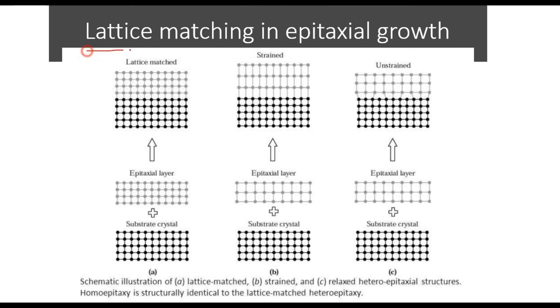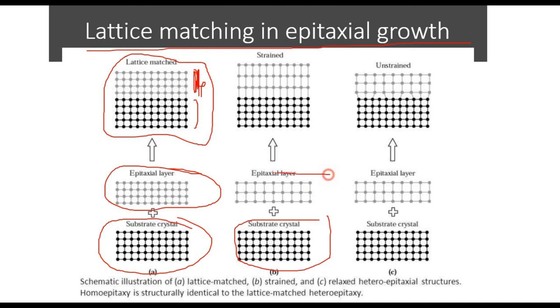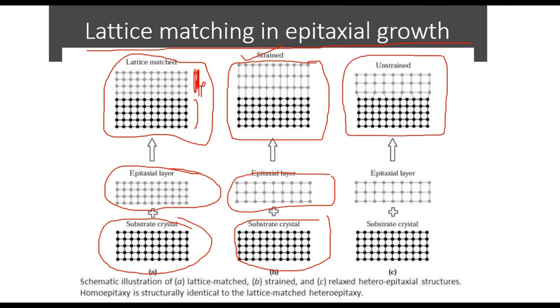This is a very important concept: lattice matching in epitaxial growth. When growing an epitaxial layer on a substrate, we must consider that the lattice should match. If the lattice of the substrate crystal and the epitaxial layer match, that is ideal. If they do not match, that is a condition of strained epitaxial growth. There is also unstrained epitaxial growth, where the interface crystals are much more relaxed than those present at the substrate.